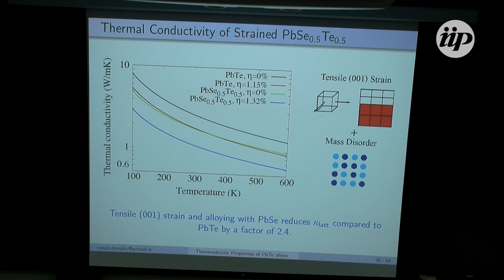And now what happens to the thermal conductivity? You get this blue curve here, where we see it's reduced by about a factor of 2.4 compared to that of lead telluride. Again, by combining these effects of increased proximity to the phase transition to increase that TO acoustic interaction and the effects of mass disorder from the alloy.